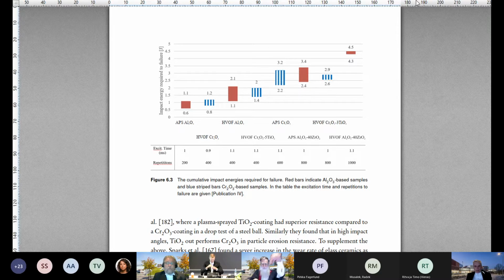Yeah. So rather than testing on the surface, on the lamellae, you're testing on the edge, horizontally on the cross section. Well, that's an interesting one. It would certainly remove the substrate influence. The cracks, potential cracks going downwards, wouldn't stop. They could propagate to infinity. But otherwise, there would be mostly a lot of cracks between the lamella, so in that horizontal direction, at least more than in the vertical one.